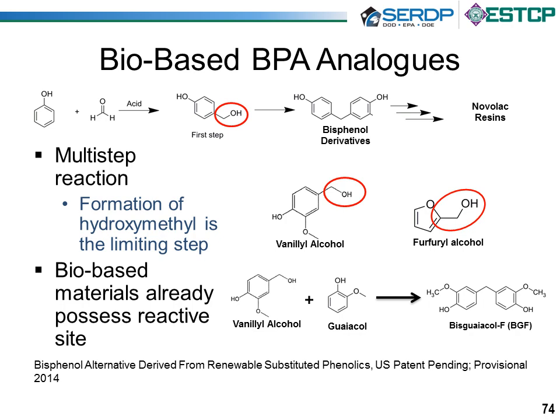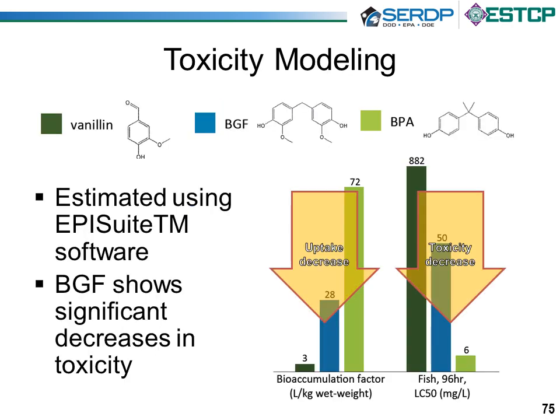What we found is the toxicity of these materials is significantly reduced. We did this through QSAR measurements, where we show that the BGF bioaccumulation is much less than that of BPA, and the aquatic toxicity, in this particular case, is more than an order of magnitude lower for the BGF relative to the BPA. So results indicate that these materials reduce toxicity, and we're in the process of experimentally measuring the toxicity to determine that as well. So far, some preliminary results we've achieved have indicated this as well, but we have not completed that, so we're still waiting on those.